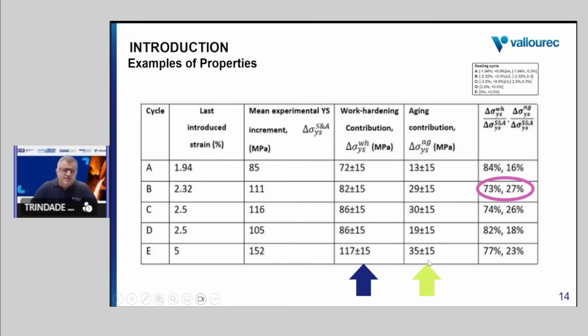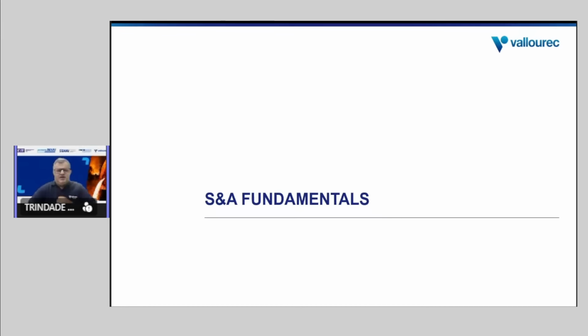Here is another very important finding for the industry. As I told you, for the increase in the strength, we should have two contributions, one from the work hardening and another coming from the aging process. When we see the contribution of each one individually, the increase in the strength by work hardening is much more significant than the increase from the aging process. In general, we are talking about 70% of the increase due to work hardening, and 30% due to the aging. This is another important thing for the industry. This is a fact, an experimental observation in extensive lab tests.